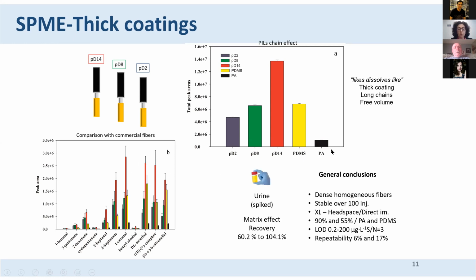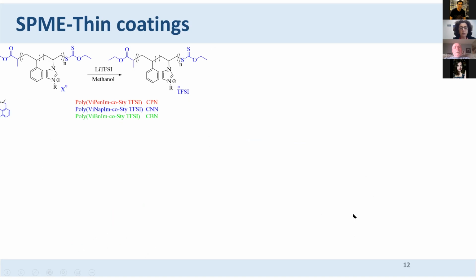This work was done on spiked urine so that we had the matrix effect and we could see the recovery. The recovery ranged from 60 to 104, and repeatability was quite good, between 6 and 17, taking into account that this was his first work. However, what he noticed is that it was too thick, and the materials that were sorbed inside took a long time to desorb and to recover. And so the idea in the next work was to develop what he called the thin fiber.